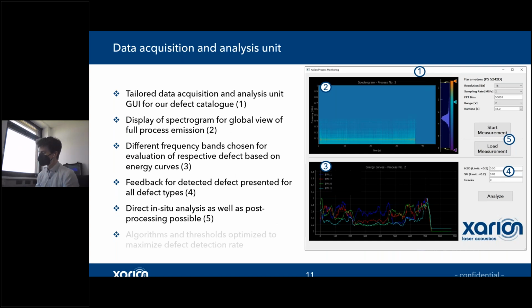So that was on the defect catalog side. The second thing was to develop a software interface, a GUI, which enables us direct feedback about these 3 defect types. And what you see on that software is, first of all, the spectrogram, the acoustic fingerprint of the entire process, that's very helpful just for orientation. You then see the energy curves. So these are really the curves within the 4 specified frequency bands, which allow us to find the defects.